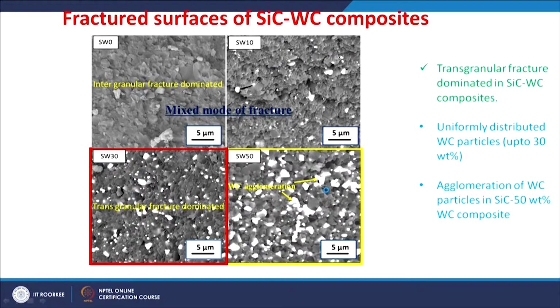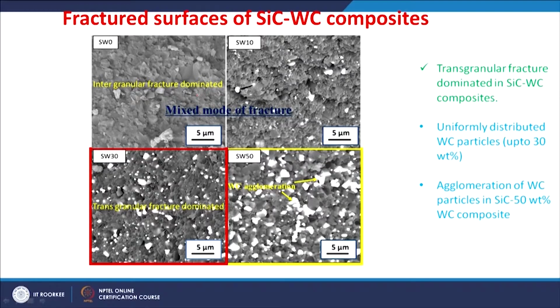The fractured surfaces of these composites show mainly intergranular fracture dominating when no tungsten carbide was added. It is simply pulling out of these SiC grains. When tungsten carbide is added, transgranular fracture dominates. So, you can see the silicon carbide grains are fractured. This difference in the mode of fracture from intergranular to transgranular is going to help in the improvement of properties.